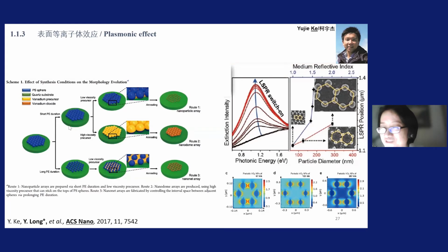Okay, so a lot of experimental and lab work, trying to control the viscosity, the plasma etching time, and also the different precursors, so that he can get all sorts of structures like nanoparticle arrays, nanodome and nanonet. And he focused very much on these nanoparticle arrays. So he reported this LSPR switch on and off, because as I said, LSPR only happens at the metallic phase. So switch on and switch off. This is definitely one of the very first. Because all the other people talk about gold, silver, but we talk about the tunable LSPR.